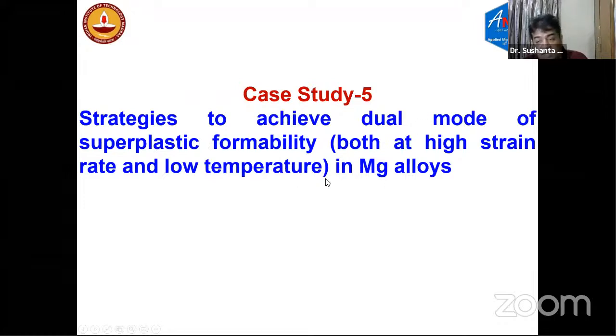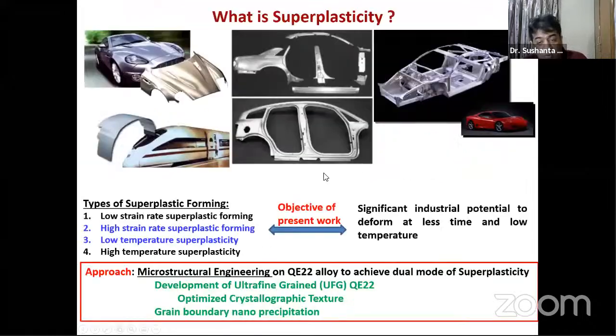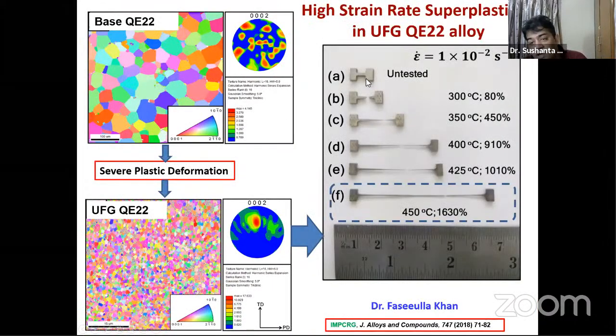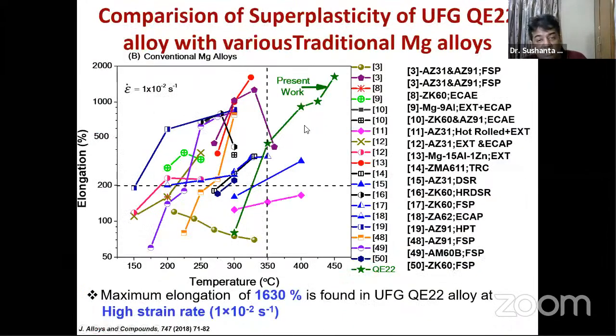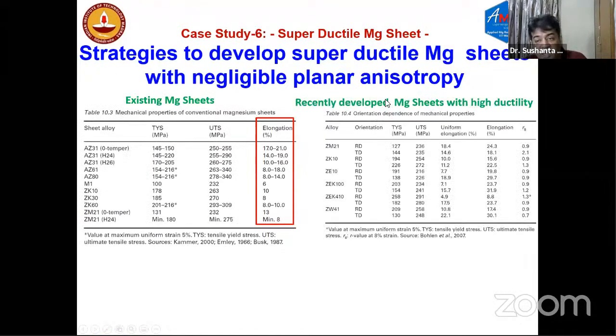In this case, magnesium has poor ductility. Here we try to improve the superplastic formability of magnesium. So we again engineered the microstructure, and we found that although magnesium is brittle, we got 1630% elongation by engineering the microstructure at a particular temperature. Magnesium is a poorly ductile, brittle material.